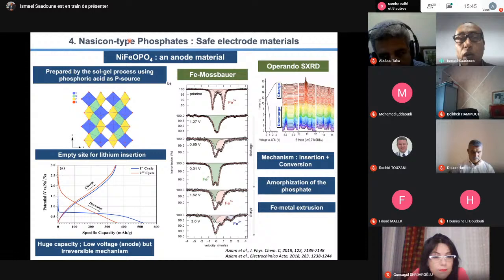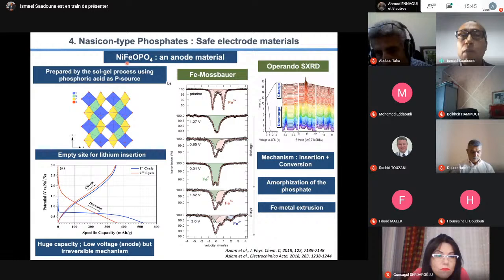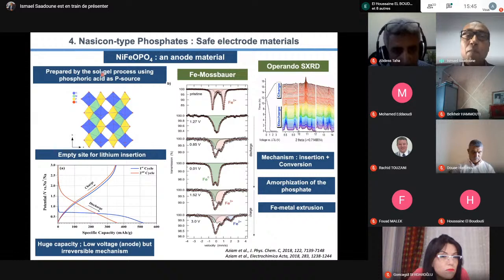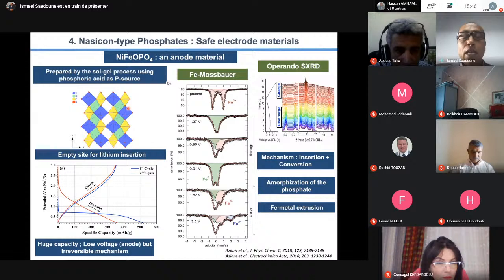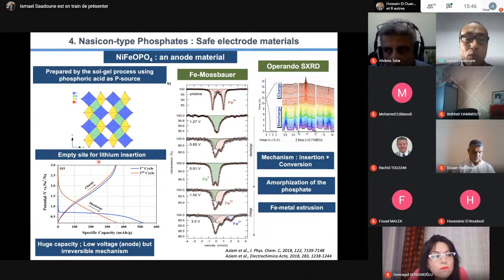Here's another one: this oxyphosphate, which, you see, without lithium, is an anode material. This is work done by Hasna, who was funded last year. You see, we prepare the same material, and you see we have some empty places here where we can put lithium, so our material can host lithium. It can play the role of anode - this is what we do.